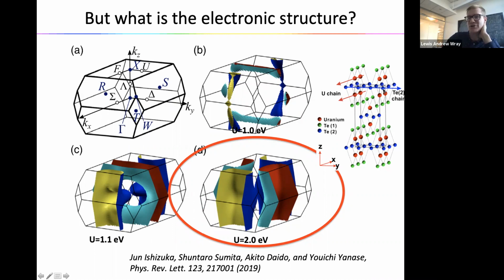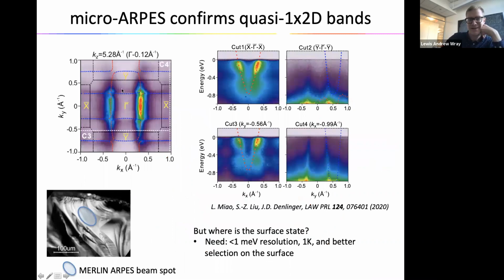There are chain structures in the material. Tellurium atoms have a chain along this y-axis. Uranium atoms have a chain along this x-axis. So uranium electrons, due to the orbitals that they occupy, can basically only move in this direction, and tellurium electrons can only move in this direction. That was the result of this study.